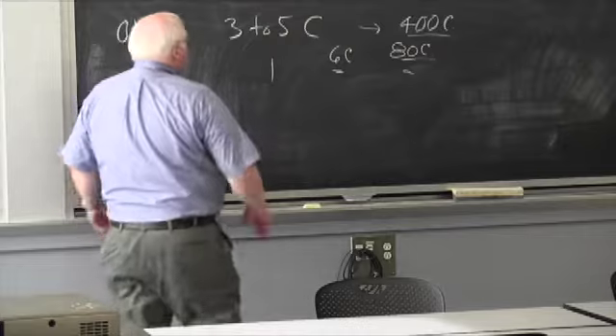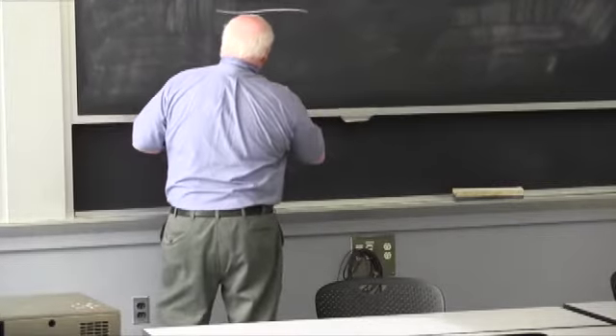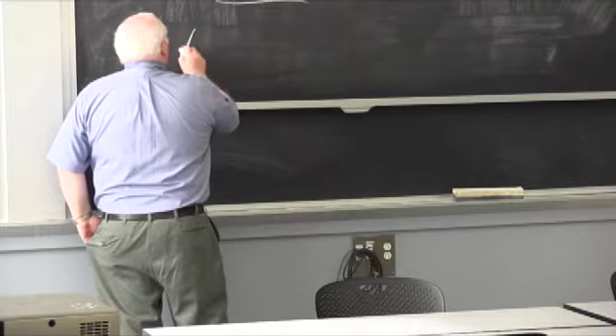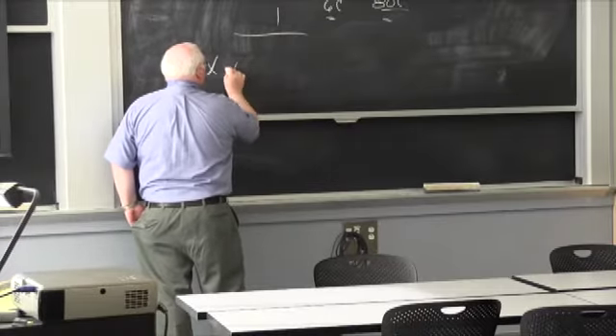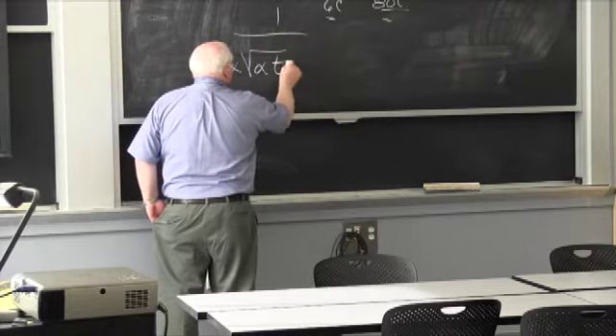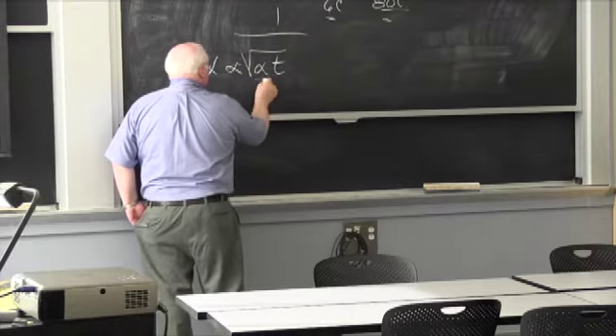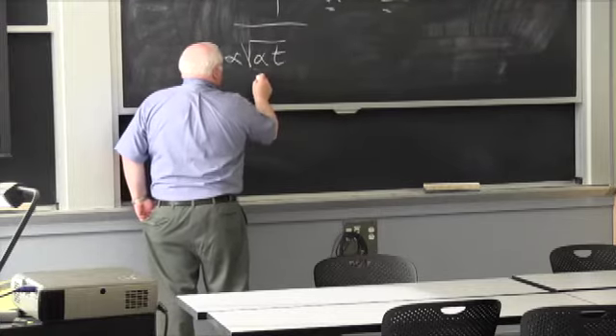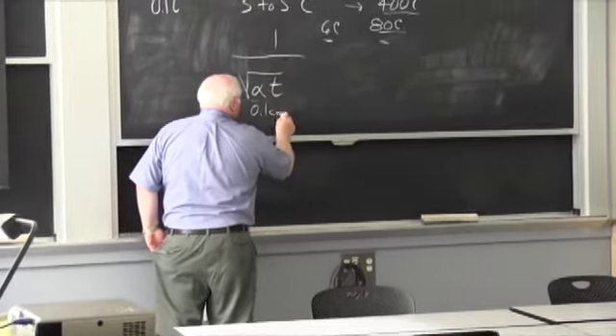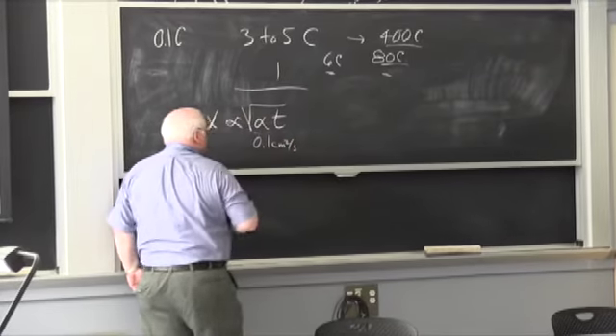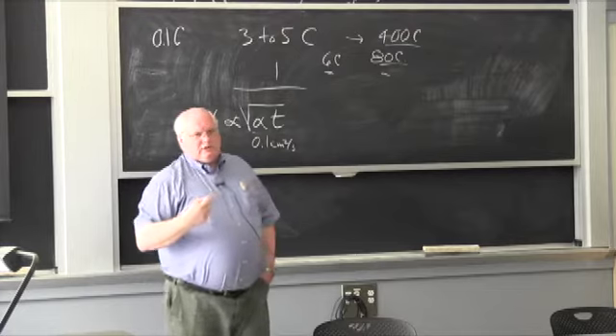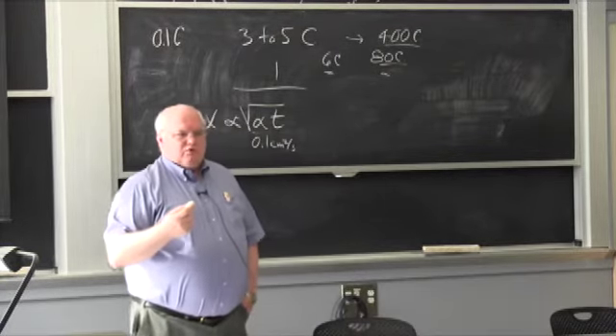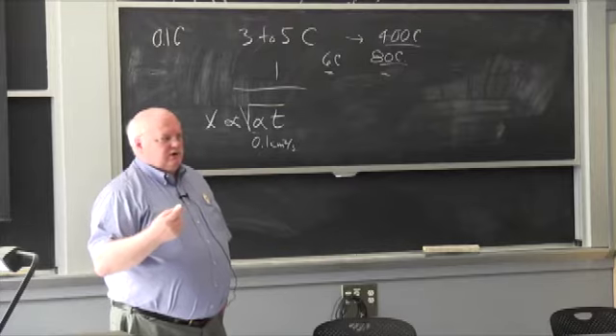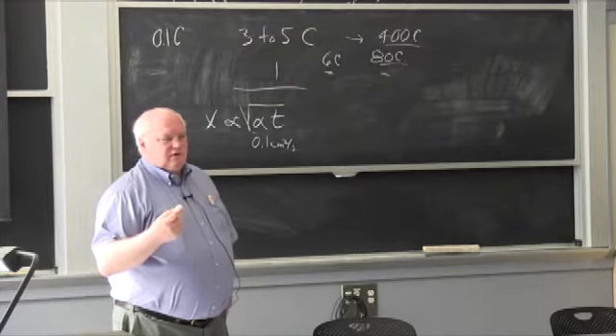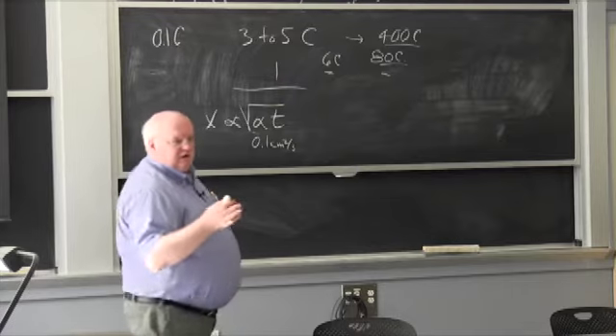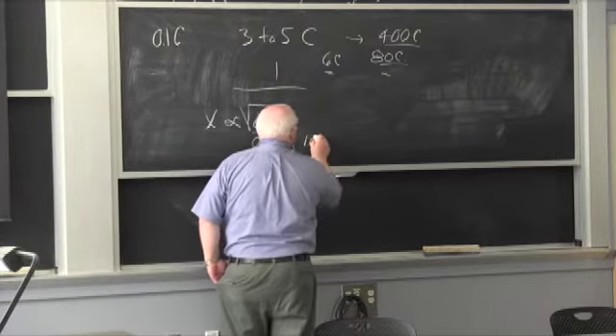If you go through in the welding section, I'll talk about the distance that heat travels in time, which is going to be proportional to the square root of the thermal diffusivity times time. This is a proportionality, and that's alpha, thermal diffusivity. The thermal diffusivity of steel is 1/10 of a centimeter squared per second, okay, and the time, if we're talking about a circuit breaker which might close, how fast will a circuit breaker close? Anybody have an idea? 1/100th of a second. Okay, half of a 60 cycle. Okay, so it's 10 to the minus 2 seconds.